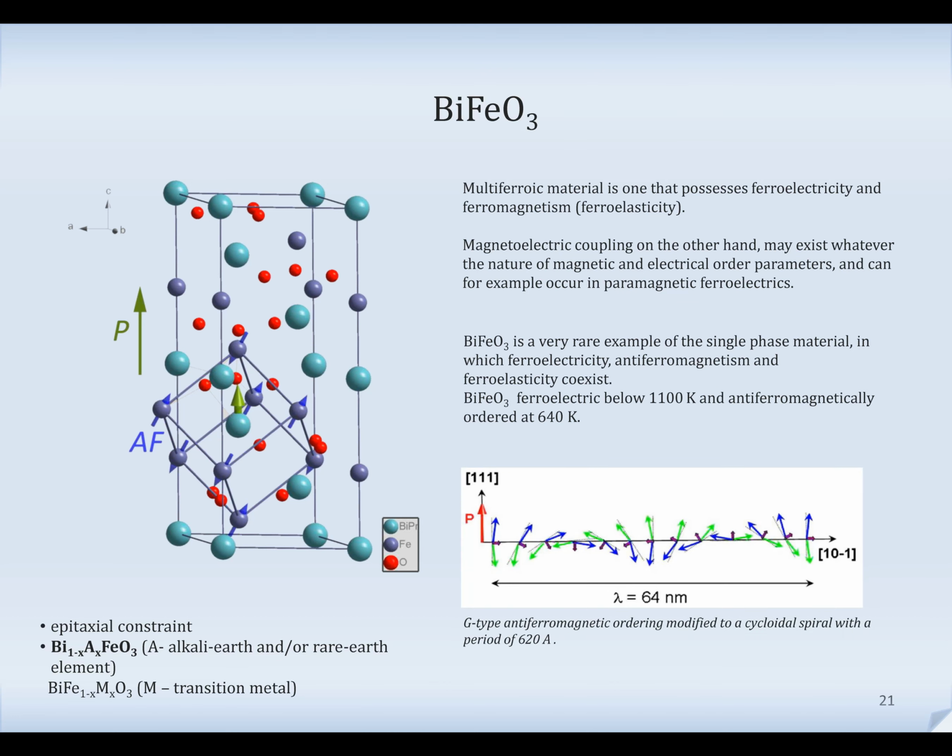And it's a polar active material, so it has polarization, mainly because of bismuth ions, which are shifted from the symmetric position, and they produce electric dipoles. And because the crystal structure is polar, we have non-zero polarization. And the idea is to improve properties of this material.